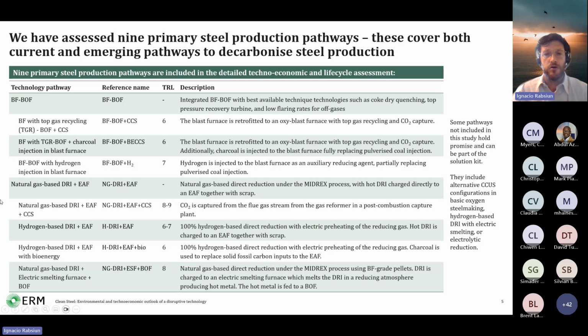One of those pathways also is combined with the use of biocarbon in the electric arc furnace. So carbon is typically added to the electric arc furnaces for improved energy efficiency, to generate some foam in the slag that improves the refining of the metal, and some process parameters that I don't want to delve into those details, but the coal that is typically used, or the fossil carbon that is typically used in the electric arc furnace, in this case, we assume that it's being replaced with biocarbon.